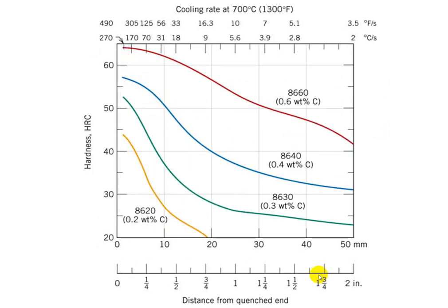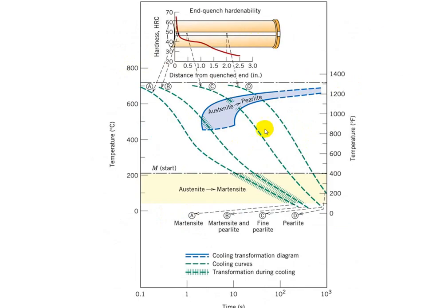So the next slide is interesting also. This comparison of alloys 8600 with different carbon content. You see, lower the carbon content you have, less hardenability and you have less hardness. So this shows that the carbon content affects both of these two qualities.